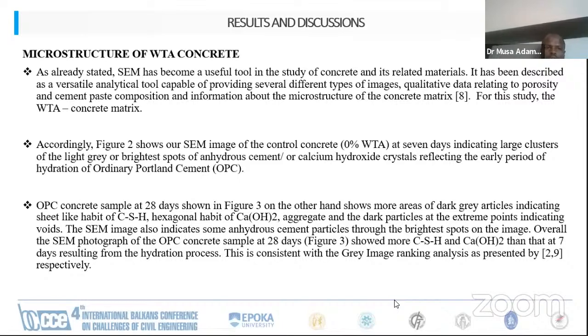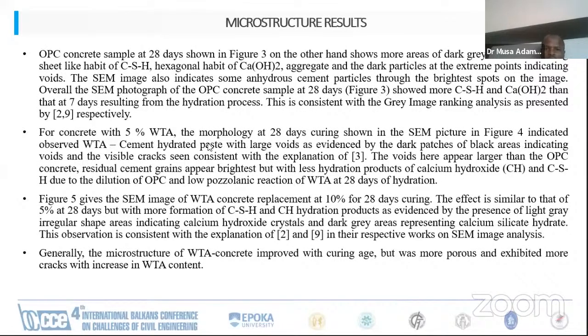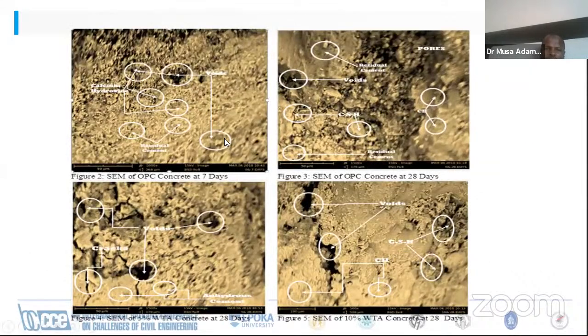Okay, so these are the calcium hydroxide crystals. These are some of the pores. We have the residual cement. Then we have the voids. We have the cracks. So these are the calcium silicate hydrates and the calcium hydroxide.